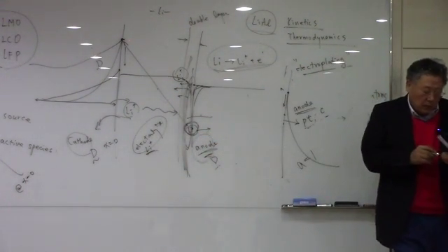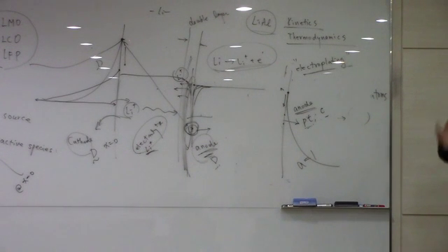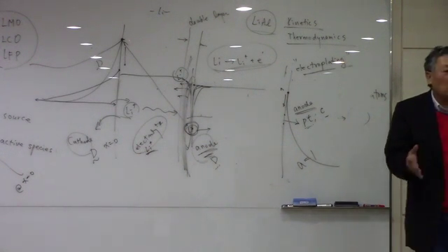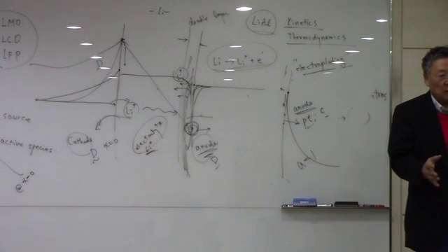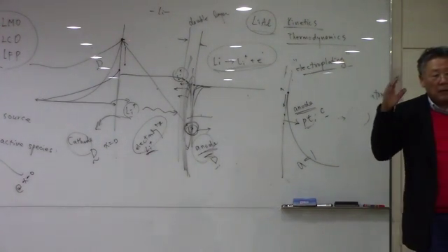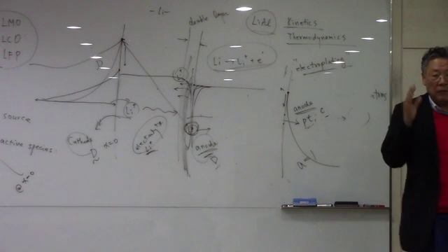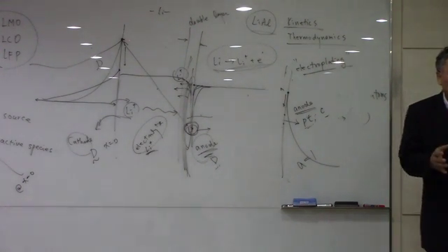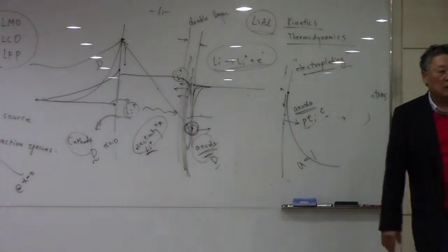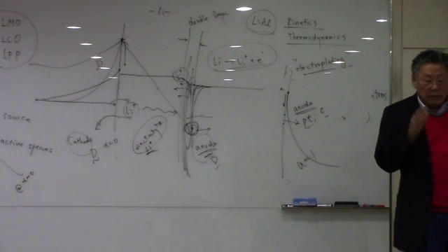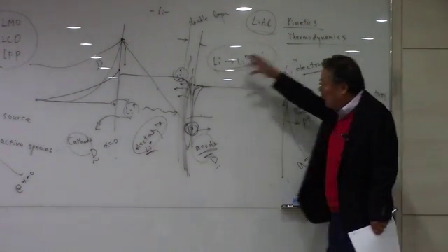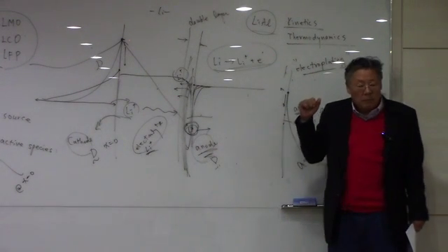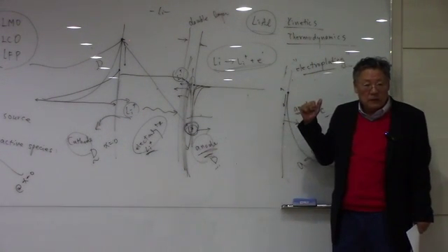So, for the anode, we do not want a high diffusion coefficient of electroactive species. But for the cathode, the diffusion coefficient of electroactive species is very critical. It should have a high diffusion coefficient to have high potentials for this.